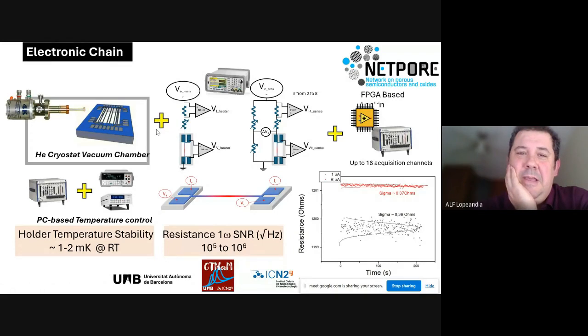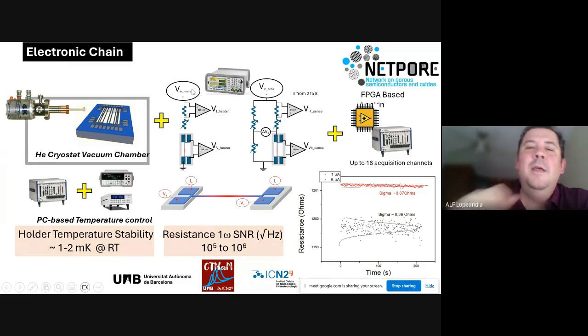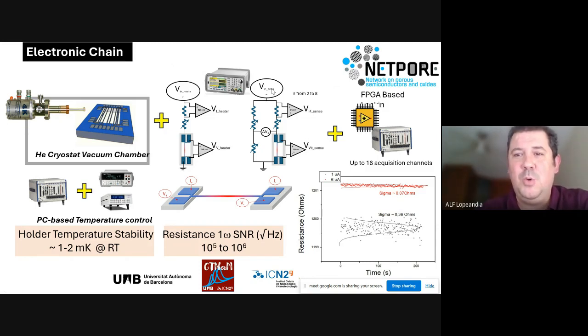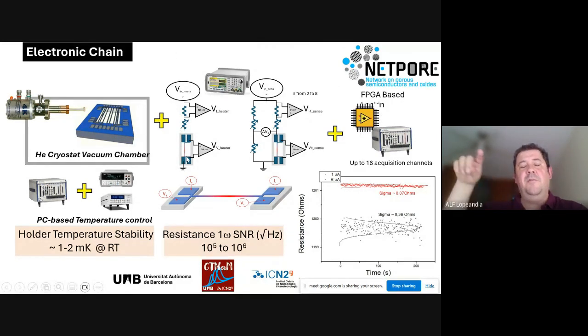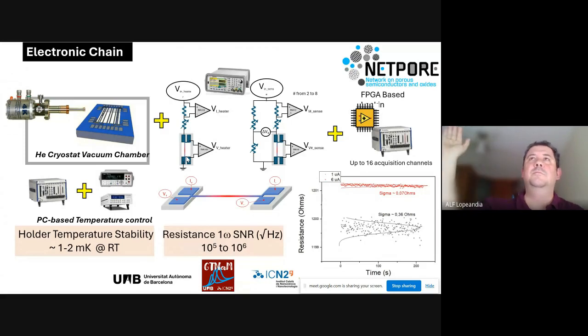Then this is the electronic chain. We have one line that we can heat up with a Keithley 6221. It's an AC current source with which we can heat up one of the lines, and we can do measurement in another line that is heated up with another Keithley. In that case, it's not the Agilent that I show here. It's another Keithley 6221. In one, we will do a staircase of currents going from, in that case, around 5 microamps to maybe 20 or 30 microamps at the end. And here we keep a constant amplitude of around 5 microamps.